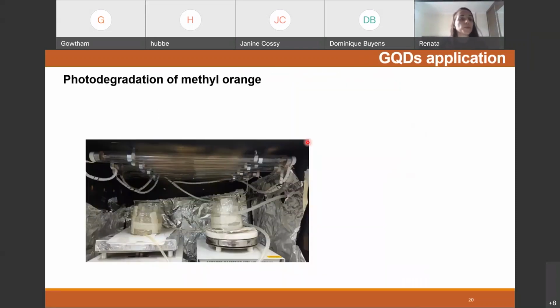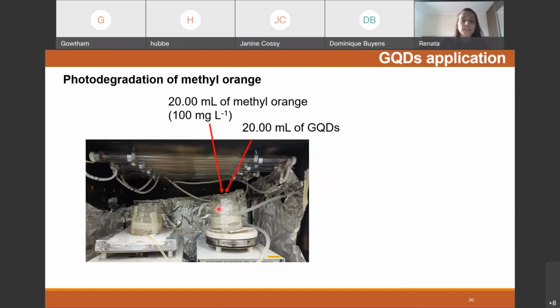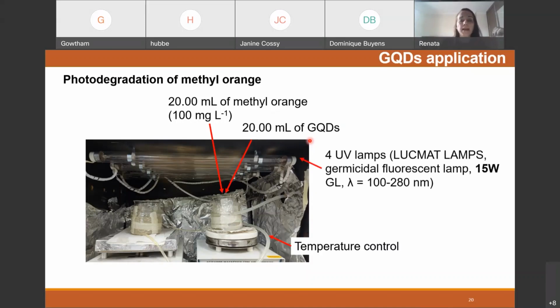Then our materials were used in the photodegradation of methyl orange. This is a photo of our system, and first 20 milliliters of methyl orange was added in a reactor, plus 20 milliliters of graphene quantum dots, our suspension. It is possible to observe that we had control of the temperature, and the system had four UV lamps.